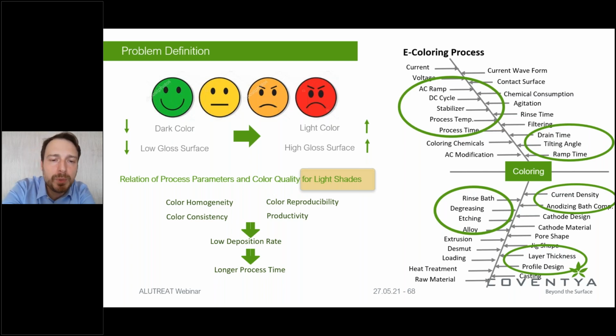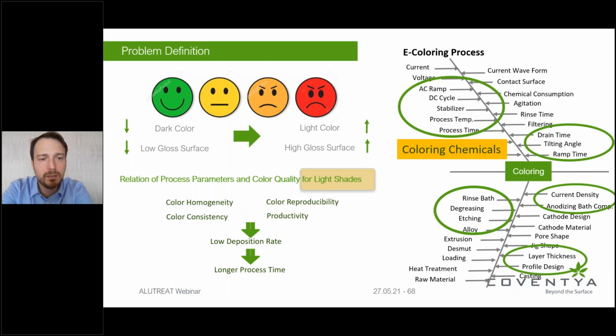Therefore, it will be much more important to have a chemistry that would enable you a lower deposition rate, hence sacrificing the chances of getting the black, but therefore a longer process time in which you can control the AC cycle, DC cycle, and also the deviations that you would have with a fast process.